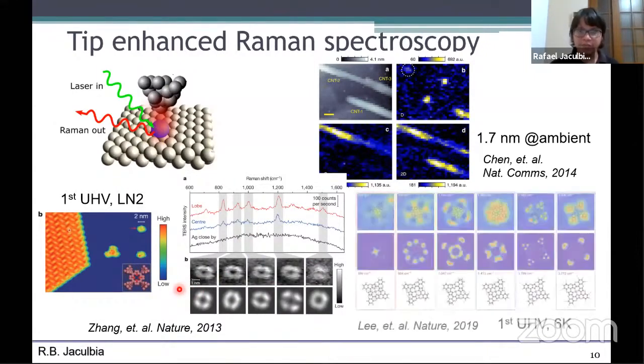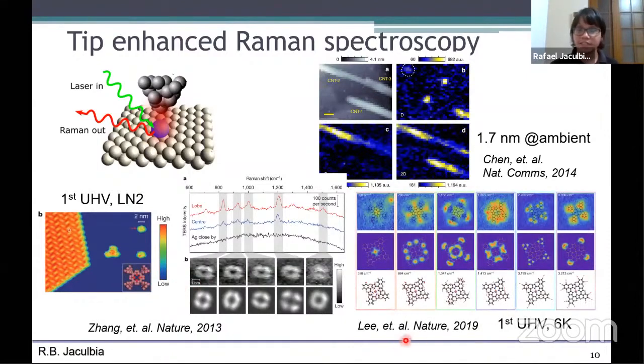And several years after, the next one was in 2019. In this situation, they were able to show that individual vibrational modes have different Raman maps. This paper was published in 2019 in Nature. Again, this is in UHV, but this time the temperature is lower, 6 Kelvin. They found, the top one is the Raman maps. So they moved the tip across the sample and across the substrate.